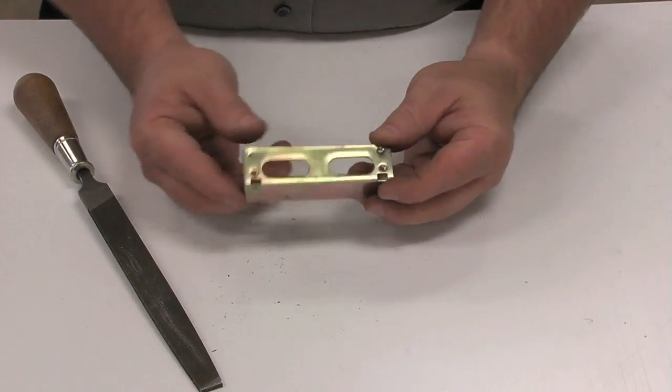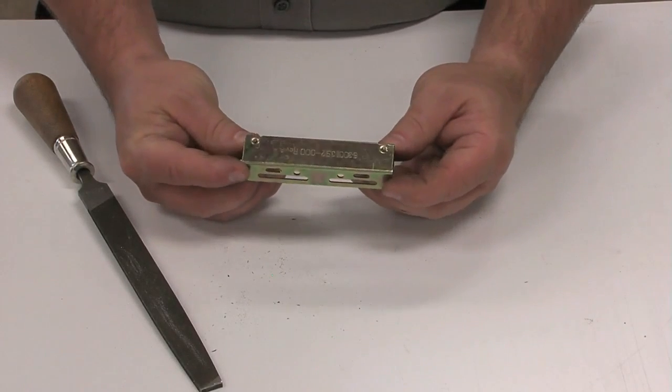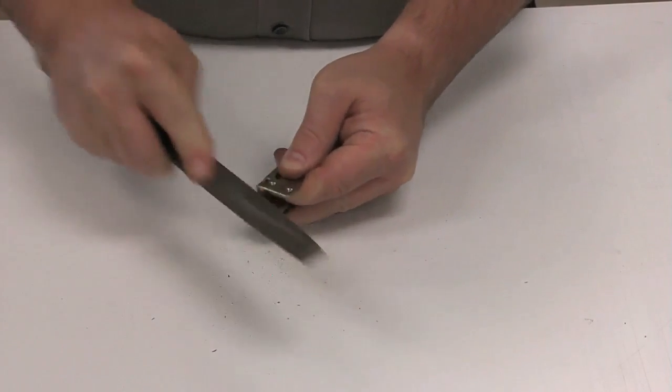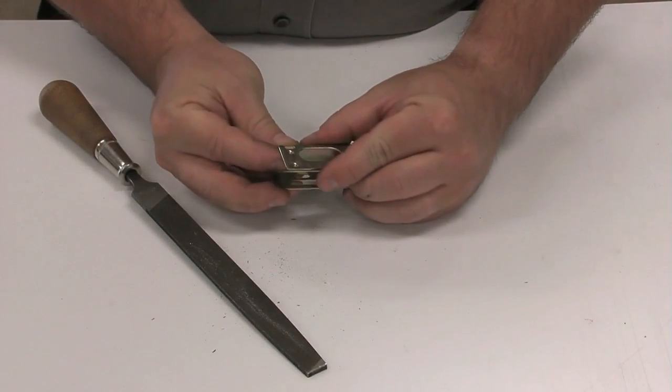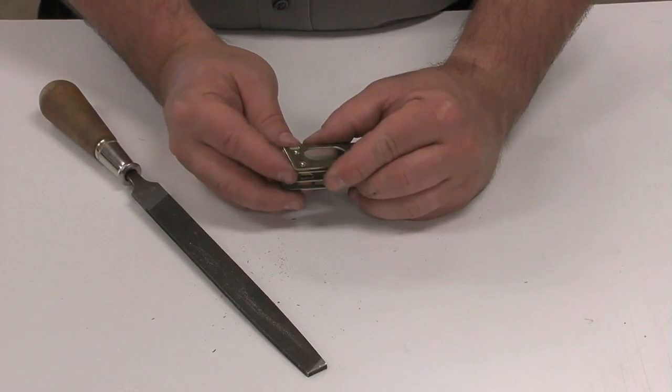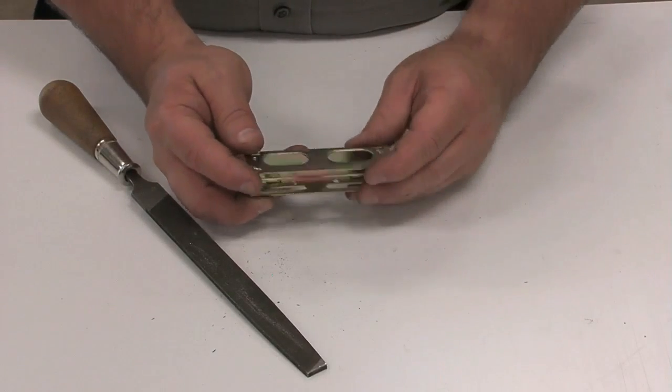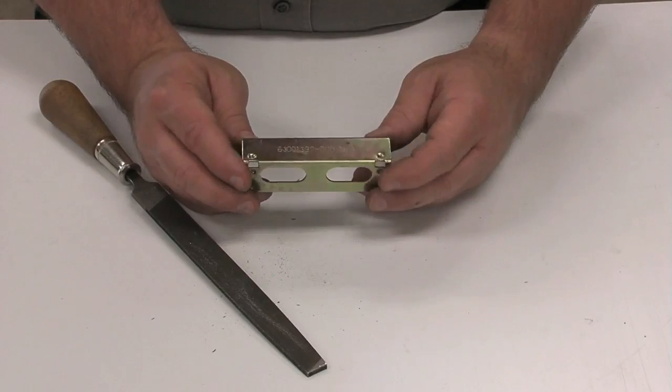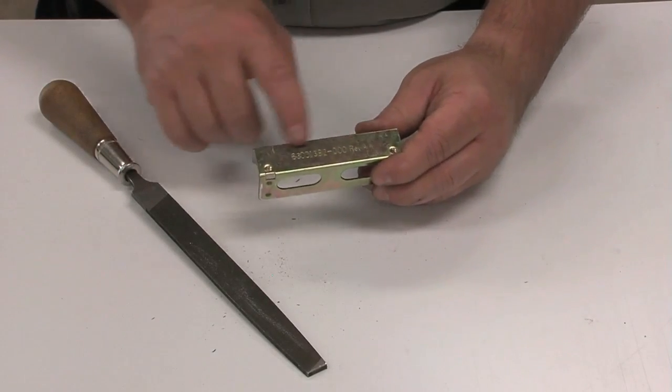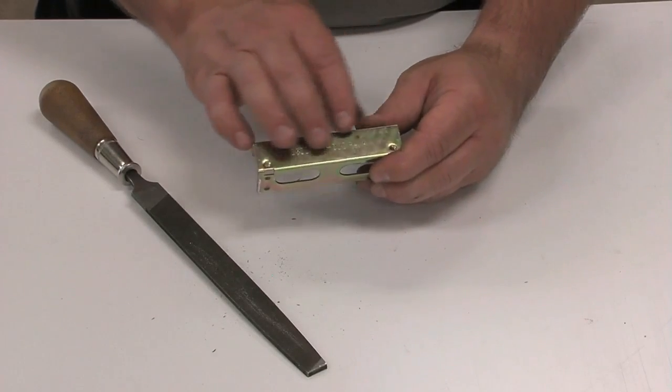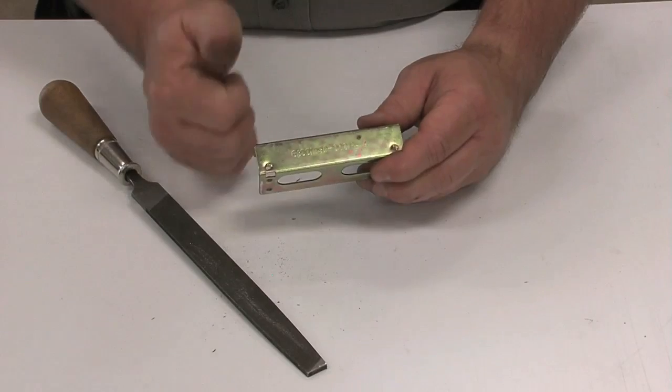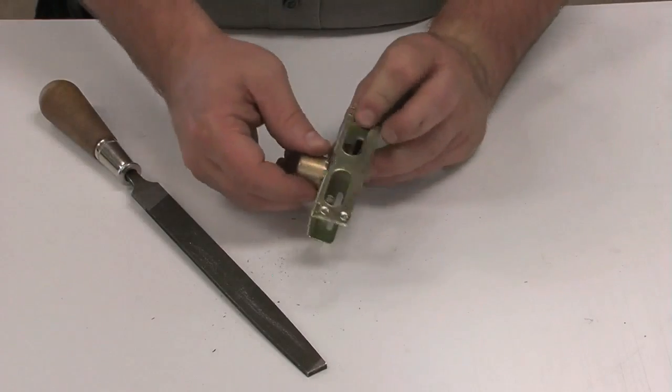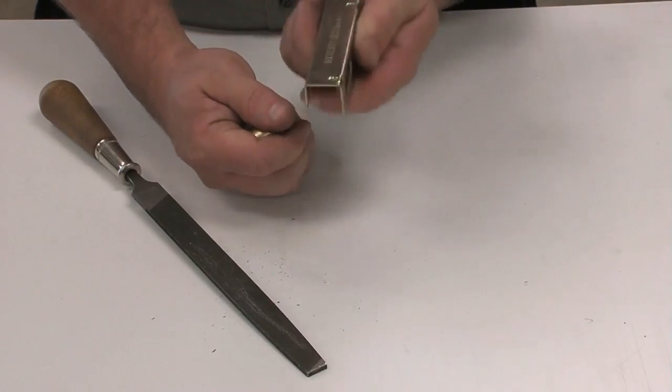Additionally, this is a piece of steel with a cadmium coating to it. Notice how gold in color it is. However, if we file through that gold coloring, we can actually see that it's silver underneath just like regular mild steel and these tend to be mild steel parts. The cadmium coating adds a little bit of surface hardness to it, but primarily it's for rust inhibiting. Again, just like zinc, cadmium is a toxic metal so anytime we heat or sand this we want to do it with either extremely well ventilated or a respirator that's rated to handle metals. It's also magnetic because the underlying material is steel.